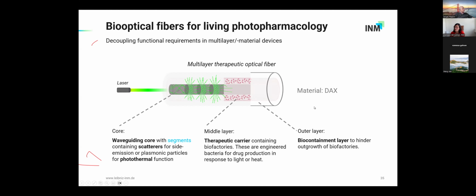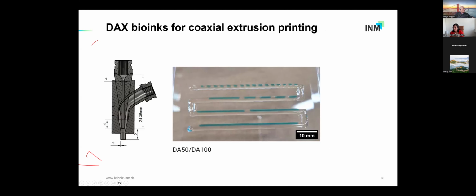Now, what's important here to note is that we are using actually almost the same material for all 3 layers, or the same ink. We are just adding scatterers or cells, or eventually also changing the ratio between the pluronic and the pluronic diacrylate to optimize the properties for the function of the layer. Pluronic is a polymer that you can print or extrude quite well. It has shear thinning properties, is actually very handleable for printing. Eventually many people are also using it as well.